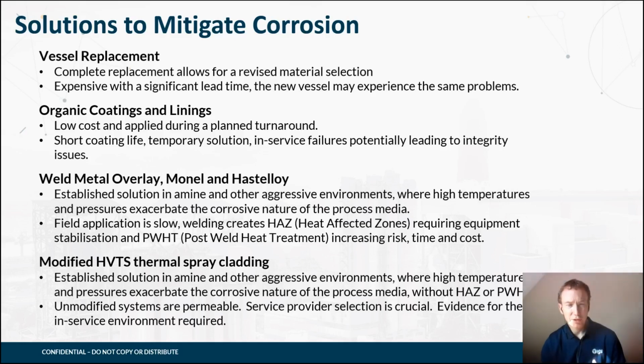They don't tend to last through multiple turnaround events, and often they're not suitable for the high temperature regions in these units. Weld metal overlay, we can install in the field a corrosion resistant alloy with weld metal overlay. This process does, however, induce a lot of heat into the substrate. We create heat affected zones. We can change the hardness of the substrate material, and that has to be post-weld heat treated in these units where we're dealing with H2S environments and with lethal service.